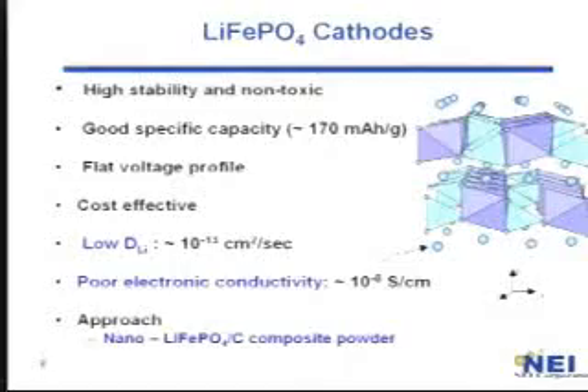Another problem with lithium cobalt oxide is that it is an oxide and it reacts with the existing electrolytes, particularly at high temperature. That's what we call thermal runaway reactions, and that can actually blow up the battery. But this has a phosphate molecule that makes it very stable, so it can be used in large size batteries. And the third interesting thing about this material is it has an absolutely flat voltage profile, which I will show in a couple of slides. So it is cost effective, highly stable, and non-toxic.